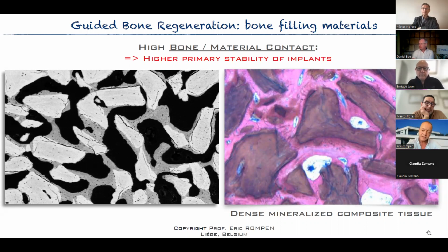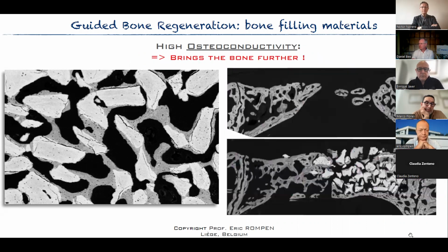And on the right side of the image, in this purple histological image, it's actually the bio-os that gives a very high bone to material contact. And the fact is that when we have a very high bone to material contact, it means that our material is very osteoconductive. So the osteoconductivity of the material is very high. And that has another advantage, this high bone to material contact, this high osteoconductivity.